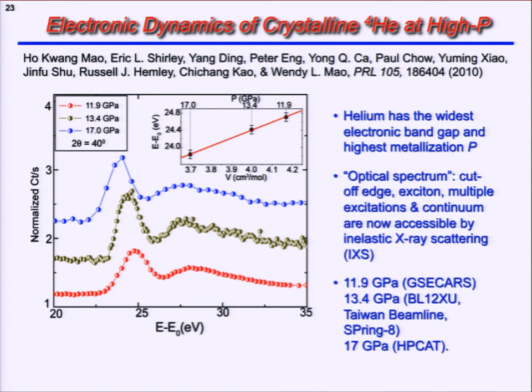Let's switch gear to another extreme material, helium. Helium has the widest electronic band gap, and so in the past, you could never really reach helium at high pressure to study it, because the diamond band gap is 5 eV and the helium band gap is 26 eV. And above the diamond band gap, diamond absorbs everything, so you cannot get an optical spectroscopy of helium that way.